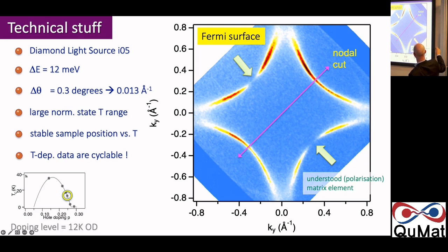So it's not quite circular, it's not quite square, it's somewhere in between. And the fact that the area inside this object is larger than the area outside this object is telling us it's hole-doped. So if you did your 2D Hubbard model with exactly half filling, your Fermi surface would be a diamond. Exactly the same number of electrons.